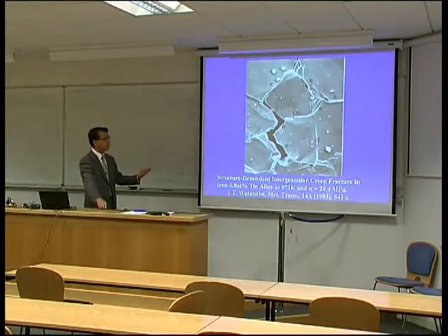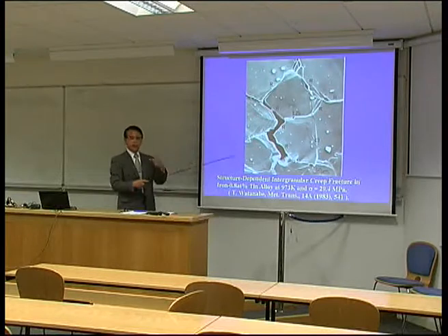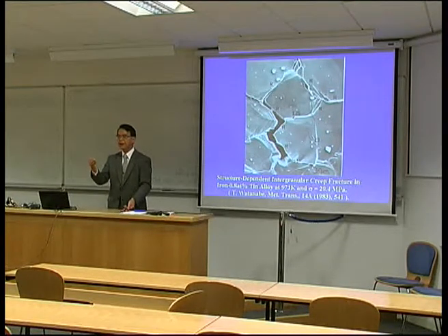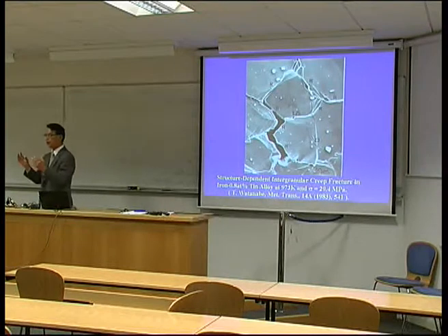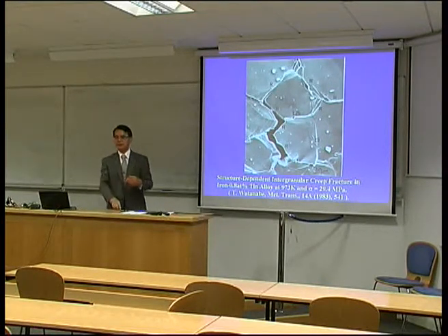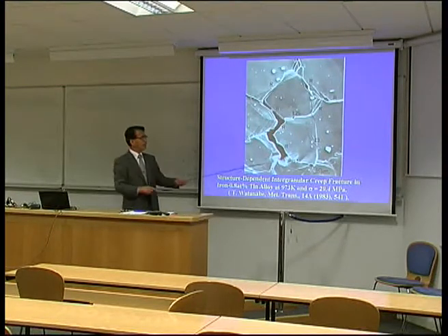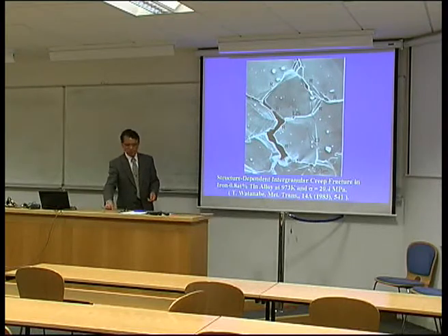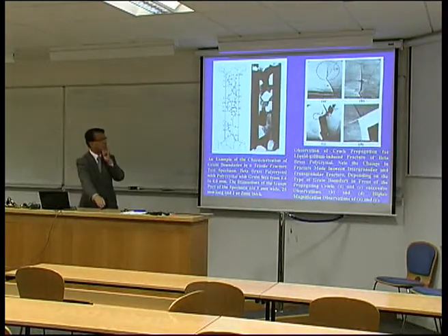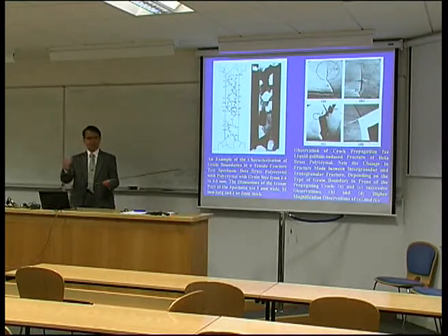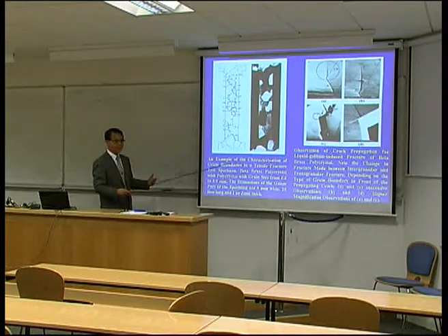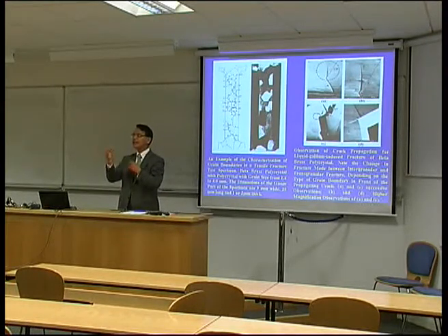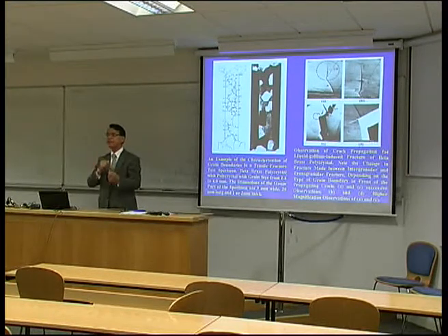But anyway, another important thing is that in real polycrystalline matter, how different types of boundary are connecting to each other is also important. Most metallurgical phenomena often occur by a percolation process, because the paths of the sites are connecting in two or three dimensions. So this is also important. For example, in the case of intergranular fracture, this is, in my opinion, how the brittle or ductile transition occurs due to the change of fracture mode.